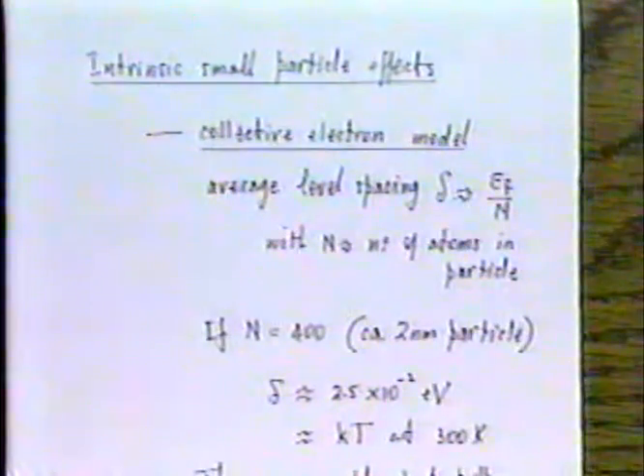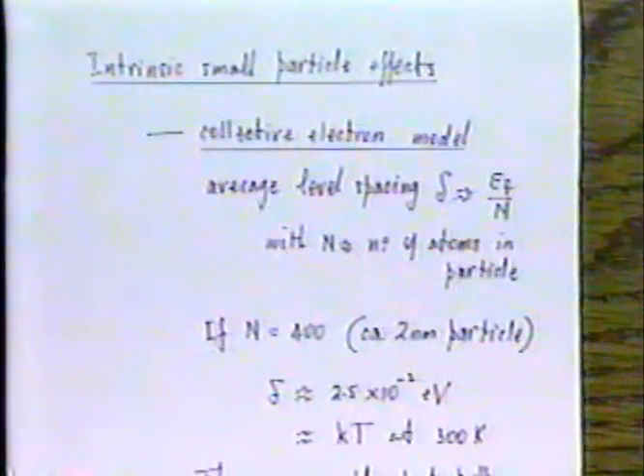From memory, the work function of platinum is about 5 electron volts. The first ionization potential of a single atom of platinum is well in excess of 8 electron volts. And so if you ask the question, what happens to the energy required to remove an electron from a lump of platinum as I reduce the size of the lump, there comes a time when the energy required to remove an electron must change, even though it may be quite a small particle before the change becomes significant. And that is in fact the case. How is one to make an estimate of how small the particle has to be before the energy required to remove an electron differs appreciably from the work function of the bulk metal?